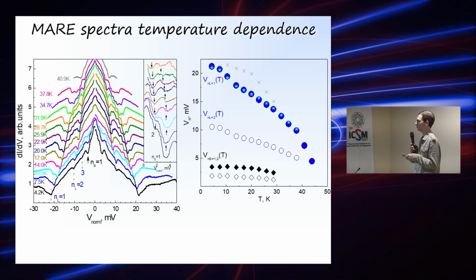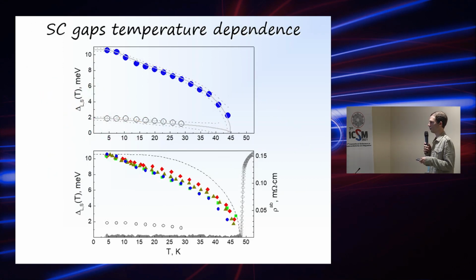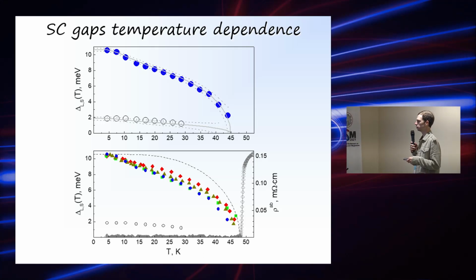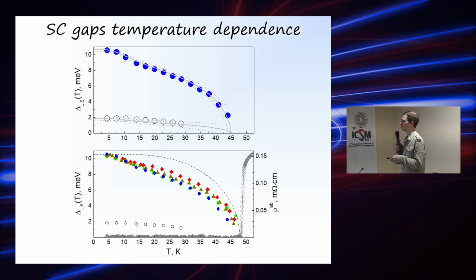As we did for the first and second Andreev minima, and also for the possible small gap, we replot it to the temperature dependence of the order parameter. Blue points are the large gap and empty points are the small gap, the probable small gap. We could show that it could be fitted by the trivial Moskalenko-Suhl temperature dependence, by the theoretical dependence, these green lines. So it could be both gaps, but probably the input of the effective zones with a small gap in this compound is very small, the same as the conductivity.